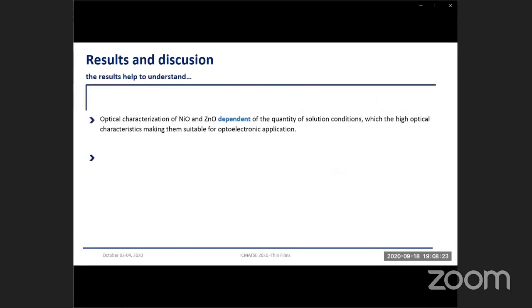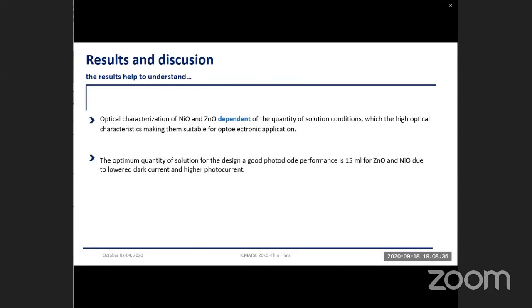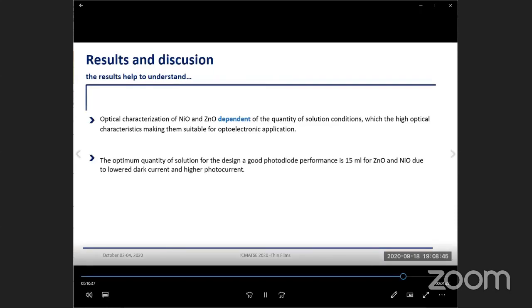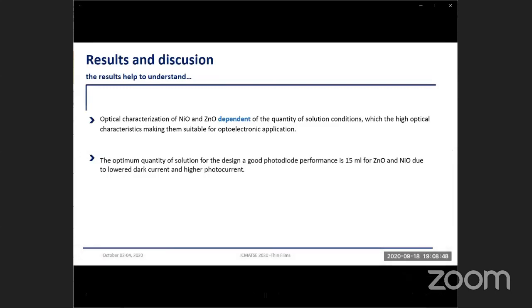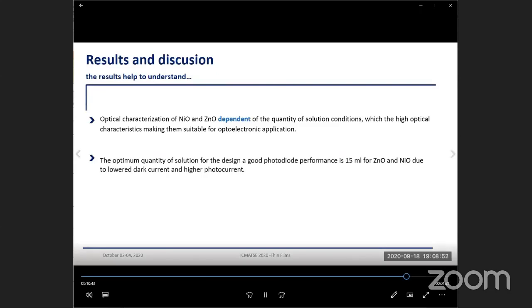optical characterization of nickel oxide and zinc oxide depend on the quantity of solution conditions, with high optical characteristics making them suitable for optoelectronic application. The optimum quantity of solution for the design of good photodiode performance is 15 milliliter for zinc oxide and nickel oxide together, due to lower dark current and high photocurrent plus high responsivity.